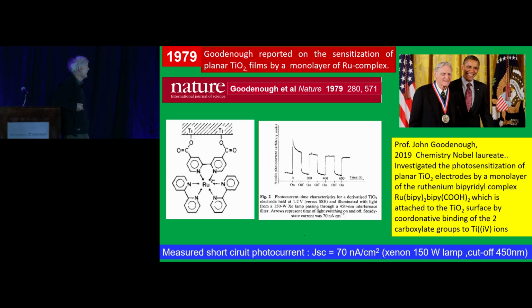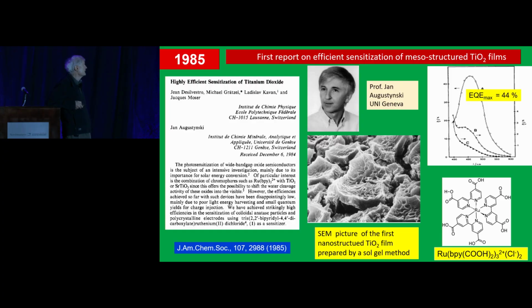But we came from a different angle. We had been working on nanostructured electrodes. And so together with our colleague, Professor Augustynski, we made a sol gel film of TiO2, which had a fractal, a large surface area. And the first results looked very encouraging.